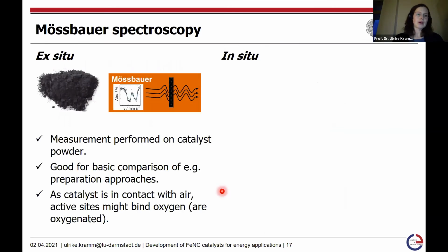So Mössbauer spectroscopy can be performed ex situ or in situ. When we go for ex situ Mössbauer spectroscopy, we typically perform it on the catalyst powder. And this is very nice for basic comparison, for instance, of different preparation approaches. Like, we have a catalyst that contains additionally some sextet species or not, what might be the effect of the pyrolysis temperature, for instance. But what we always need to keep in mind is our catalysts are intended to reduce oxygen within the fuel cell. And based on that, of course, they have a very high affinity to oxygen. And as they are typically in contact with air, you might assume that the active sites already bind oxygen. That means they are in an oxygenated state.